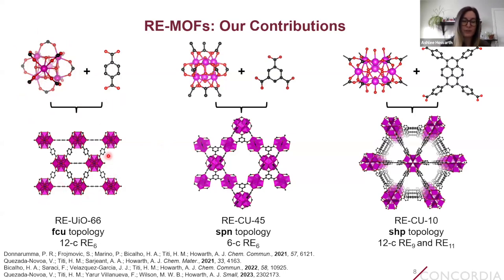So the Eddaoudi research group was the first group to show that you could make these hexanuclear rare earth clusters, and even that you could make MOFs with fcu topology. But my group was the first to actually use the terephthalic acid linker, the original linker of UiO-66. Now we can also make, and we have also made, rare earth analogs of a MOF called MOF-808.